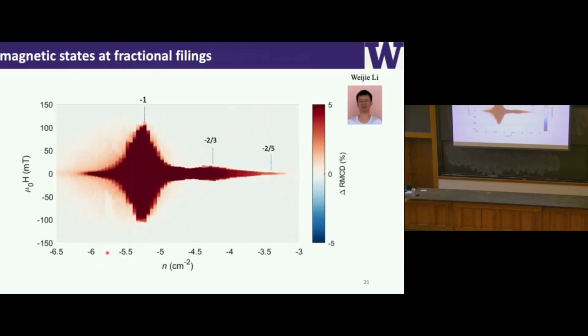Then we can also just plot the hysteretic component only, okay? And as a function of doping, as I show here, the vertical axis now is magnetic field. So this plot is basically showing how the coercive field changes as a function of doping. Now you can see the coercive field is dramatically enhanced at the integer filling -1, and also enhanced at the fractional filling -2/3, and also a little bit at filling -2/5, etc. Now we all know that -1 is a quantum anomalous Hall state, and -2/3, -2/5 are fractional quantum anomalous Hall states.